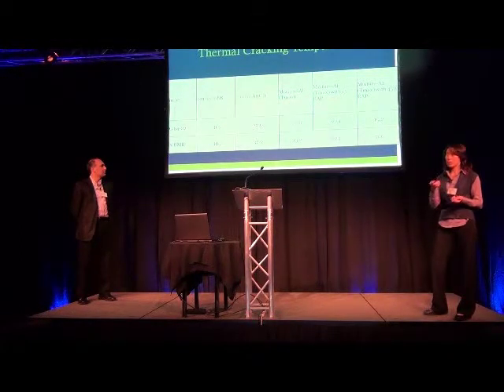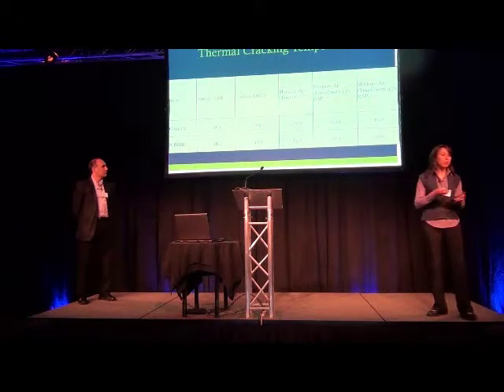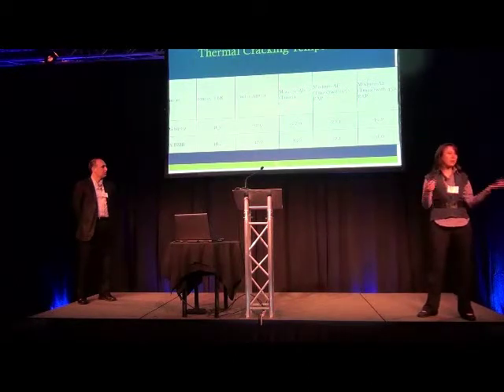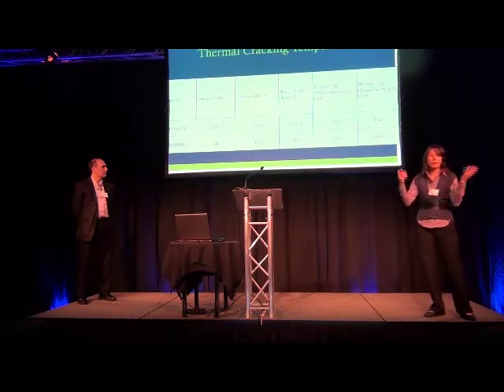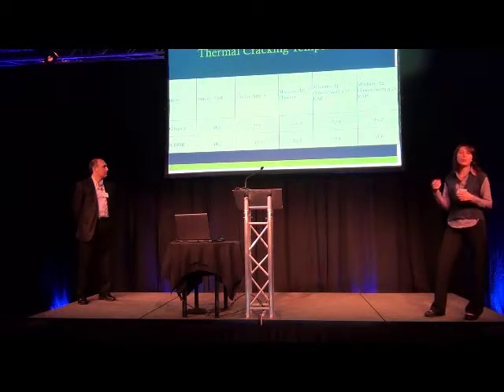So we tested almost every cracking test that is available in the US and Europe. These are the tests common in the US. This one is more common in Europe, and so is this one. And of course the numbers are different because the geometry, the mode of loading and so forth is different. We wanted to see if you test it with different tests, whether the result is consistent or not. Are we getting improvement with all these tests in different countries and so forth? And the answer was yes. So this is a typical asphalt. This is the modified version. You can see each one of these columns has an improvement, a different amount, but still an improvement. So that was interesting in terms of cracking. So we proved that yes, the cracking resistance at low temperature is improved.